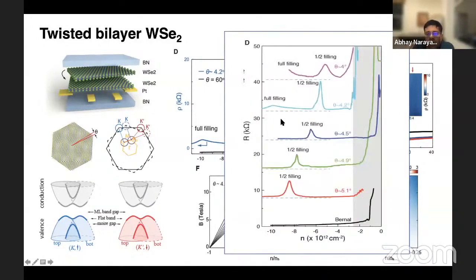Okay. Now we've done this for a range of samples which have a range of twist angles. So shown here are a few different twist angles. And if you go to different twist angles, we always see this insulating peak, but the position of this peak with density changes. And that is natural because as you change the twist angle, you're changing the size of the unit cell in real space. And so you're changing the filling required in order to fill 1 hole per unit cell. But this peak always happens exactly at 1 hole per unit cell.